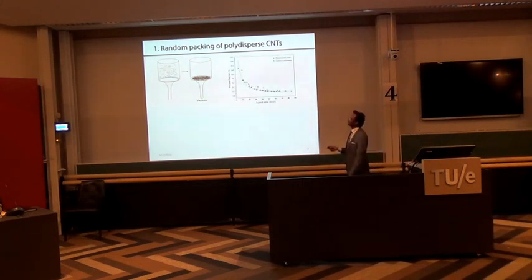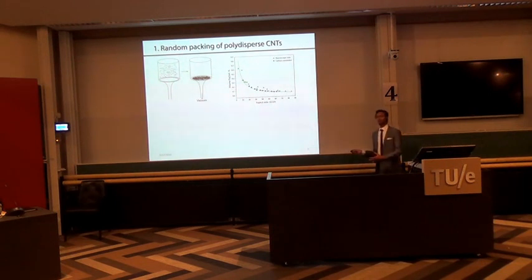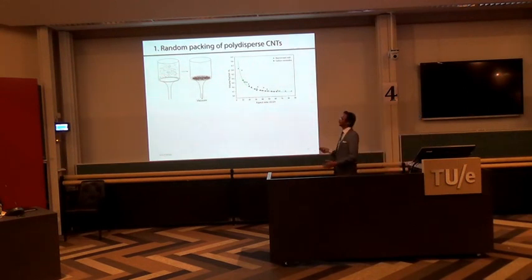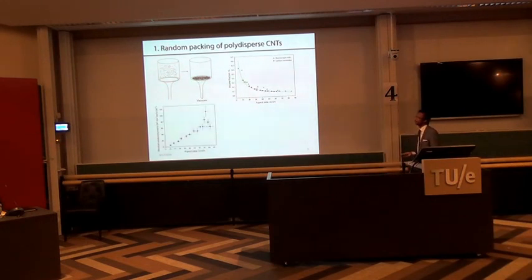The global packing analysis of these prepared carbon nanotubes matches closely with the macroscopic plots of the same aspect ratio, and this shows the continuity of 6 orders of magnitude in the packing phenomena. However, measuring the electrical conductivity shows that the network is optimized for electrical conductivity at certain specific aspect ratios. With the use of quantitative image analysis, we try to identify how the network works.